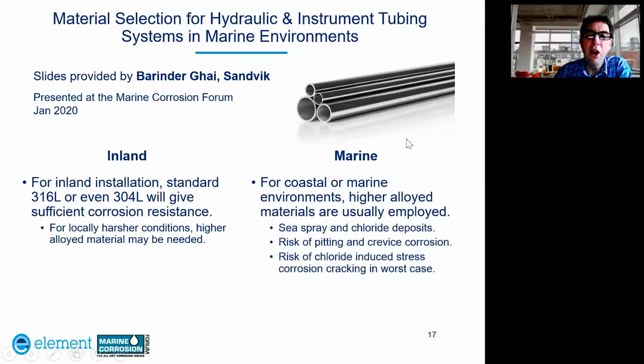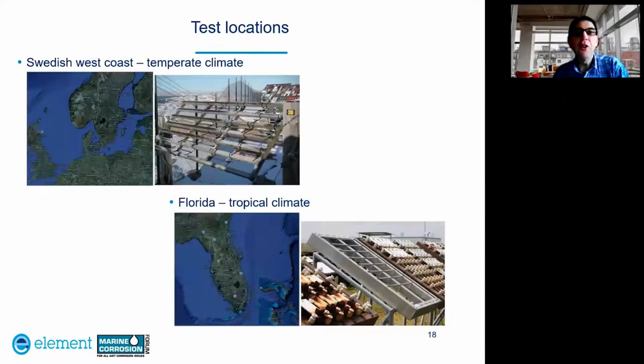So for coastal or marine environments, higher alloyed materials are usually employed. And this is due to the effects of sea spray and chloride deposits, which increases the risk of pitting and crevice corrosion. And also there may be a risk of chloride-induced stress corrosion cracking in the worst case examples. So the work conducted by Sandvik was to conduct some exposure testing at 2 locations, one on the Swedish west coast, which was considered to be a temperate climate, and the other one was in Florida, which was a tropical climate.